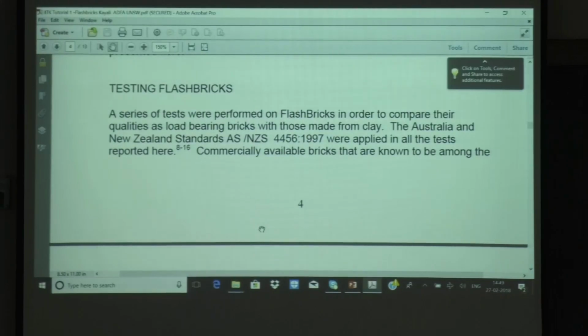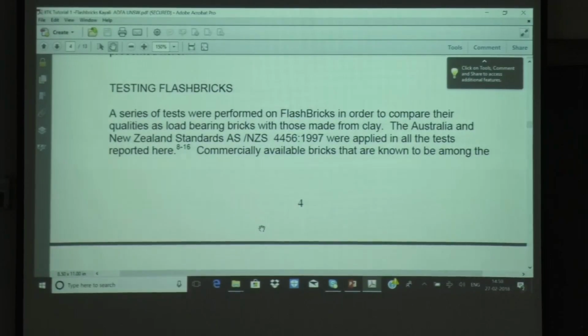So now lots of things are happening when you put it there, you're applying the fire, then much of the water goes out, and the ceramic particles which comprise the fly ash start sintering and joining together. Yes, densification. So that's what happens then. Although we said fly ash, apart from carbon, all the other components in the fly ash are ceramics. And when you are putting them together, under pressure, and you are curing or firing, those ceramics start joining with each other. Okay? So it becomes a three-dimensional bonding. All right. And a lot of water is gone.